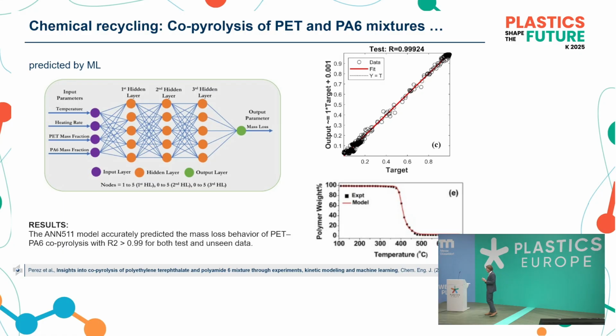It's not only available for sorting, but also at other stages along the line. One other stage, which you use for chemical recycling, is pyrolysis, to get back to an oily substance. And just around the corner, you see some examples. And here the question is, how do I get most yield out of that pyrolysis? Particularly when you have mixtures of materials like PET and polyamide 6, which often happen in true applications. So here again, you're using a neural network in order to get a max of the output based on the processing parameters which you change.